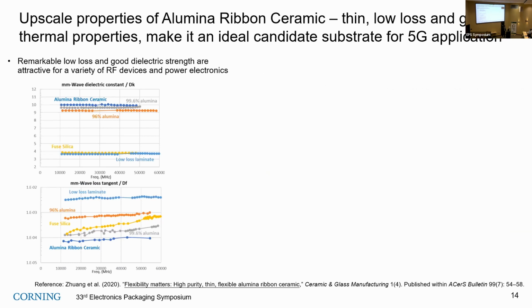Here the plot shows our frequency as a function of dielectric constant and the dielectric loss tangent. We ran the frequencies up to 60 gigahertz, and the alumina, having a dielectric constant of 10, is constant throughout the frequency range. And even for the loss tangent, compared to different doping or different compositions of alumina, our ceramic has a loss on the order of 10 to the power negative 4, and it is very consistent throughout the 60 gigahertz frequency range.